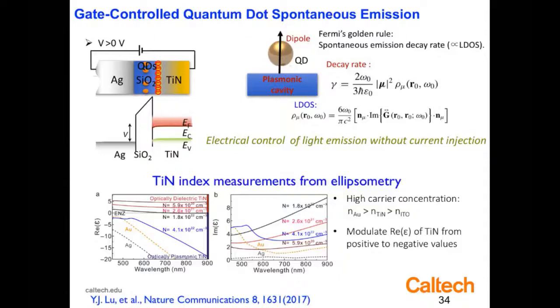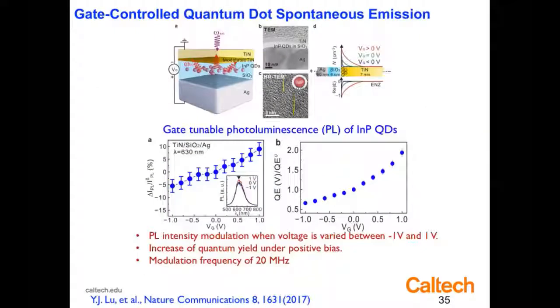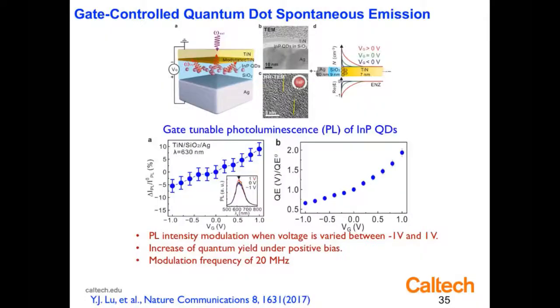And so we've been able to show that we can change the amount of light coming out, and not only the amount of light coming out, because you might say, well, okay, all you're doing is changing the absorption or reflection, but we actually measured the lifetime or the emission rate of photons, and we can see that we're actually changing the quantum efficiency. So you ask, for example, can we take a bad emitter, put it in an environment with a higher optical density of states, and make it emit radiative photons faster than the non-radiative rate? We can do this, and we can actually do it in a tunable fashion.